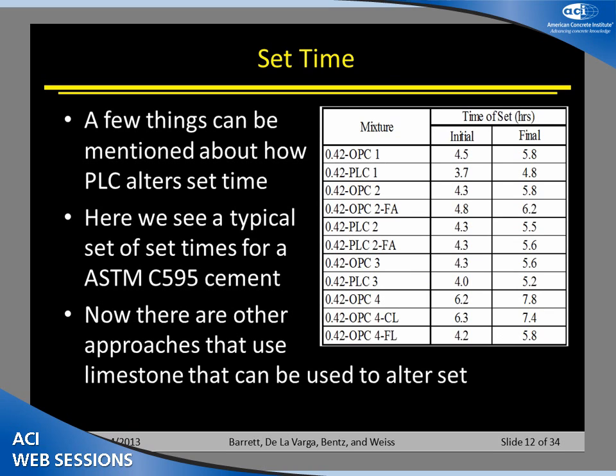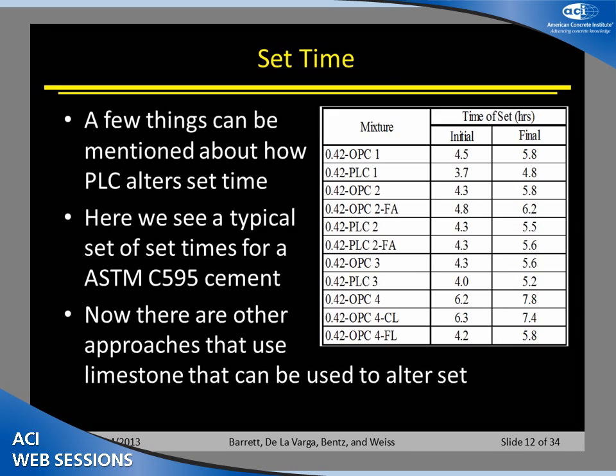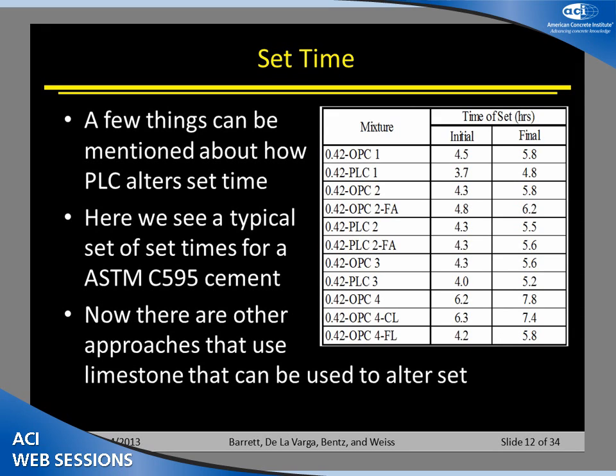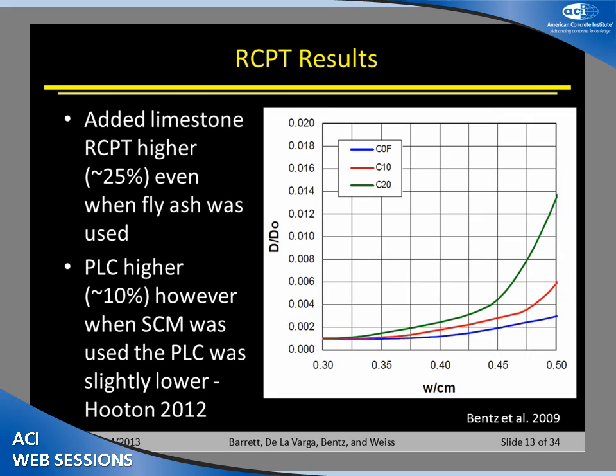Similar set times, and this will go against a little bit of what I'm going to point out a little bit later, but I wanted to put this in just as a placeholder, that when you're using the PLC system, you have a very similar set time to what you see with the OPC system. And again, I'm putting this in because it's going to contrast a little bit with what I'm going to show a little bit later on.